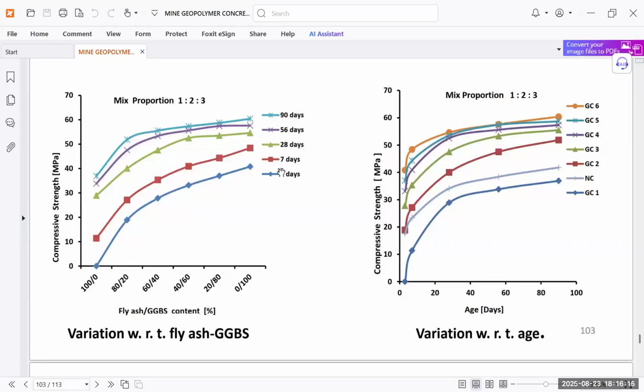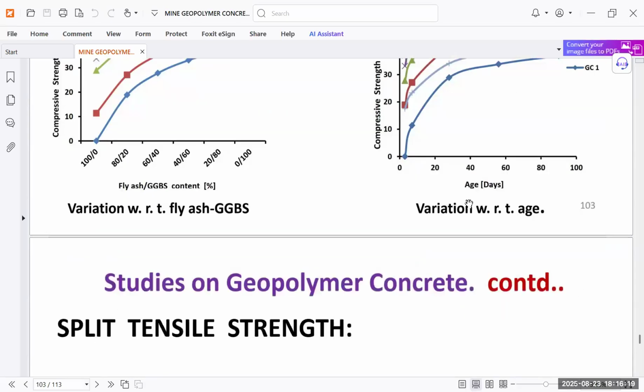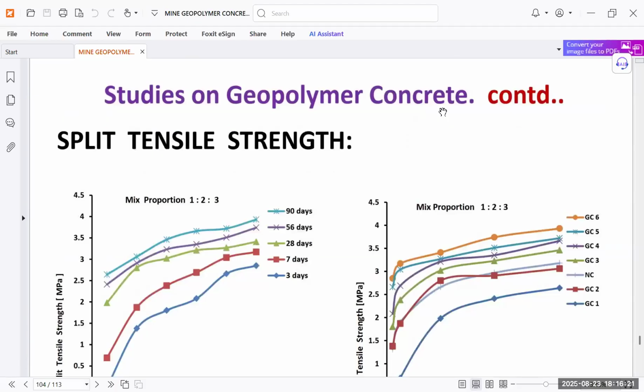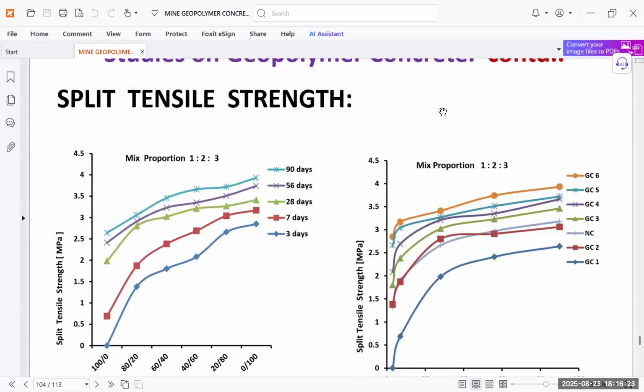We are getting this graph for different ages, and for this also we can see variation with respect to age. Studies on geopolymer concrete split tensile strength have also been done. For different fly ash to GGBS ratios, the mix proportion is 1:2:3, at 90 days, 56 days, 28 days, 7 days, 3 days. The split tensile strength is also seen, and this is normal concrete.